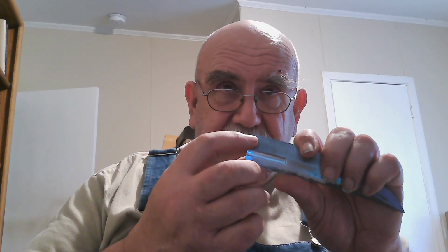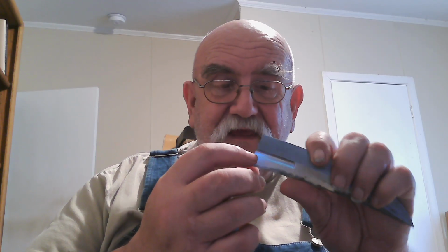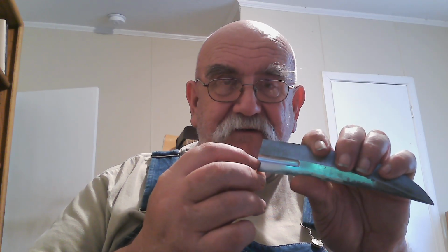So, looking at what I'm looking at, I could see when I was grinding this, everything was well and good. The blade was tempered. I'm doing the final grind here. I noticed the little black line, and I flipped it over, and the little black line was on the other side, and the ground got longer and longer into the fuller, into the bottom of the fuller, and just about to the very top of the fuller here. I stopped. And I'm looking at this, and I'm saying, it's not good.